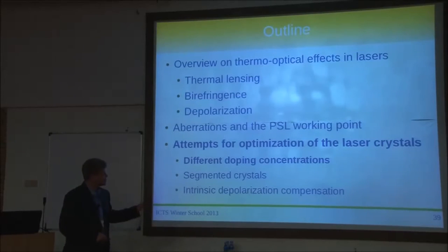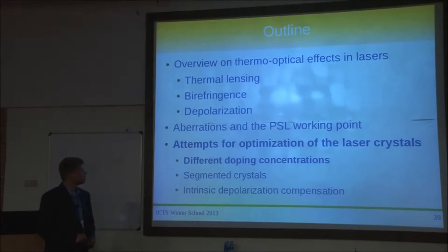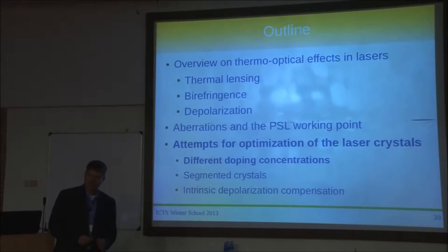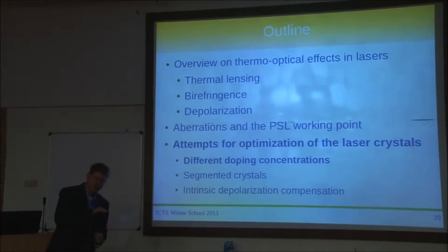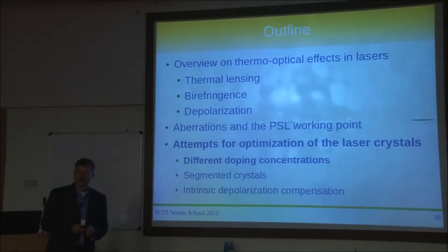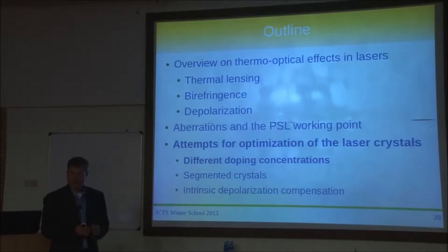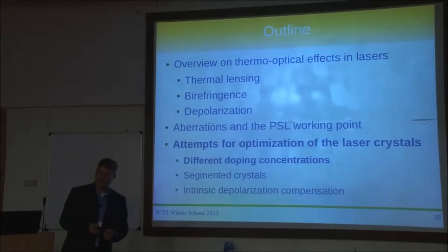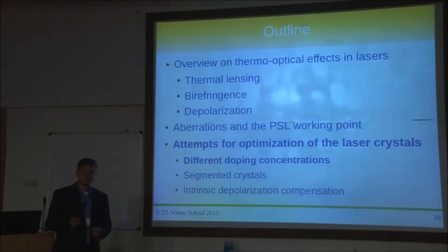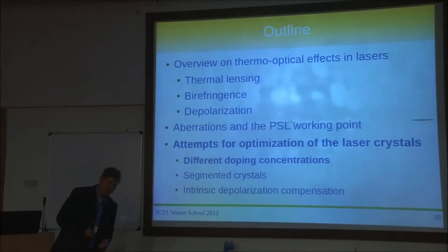One attempted optimization was using higher doping concentration. The reason is that low-doped crystals are hard to manufacture with equal quality — you can only specify something like 0.1 atomic percent doped crystals within a certain absolute uncertainty. Higher-doped crystals are more common and would reduce the percentage error in doping concentration, so we thought to try buying highly doped crystals.